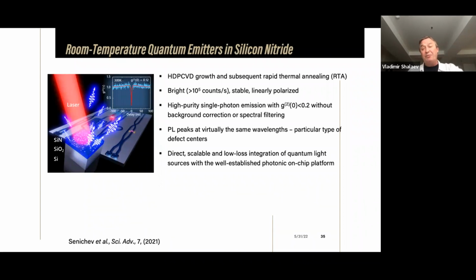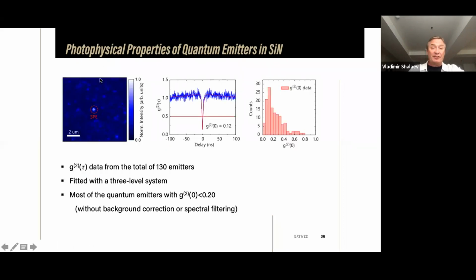Photoluminescence peaks tend to be at the same wavelength, which indicates that we are dealing with one particular type of defect center. And of course, this is a very well-established material platform, which could make a difference in terms of integrated quantum photonics. So here we just show a photoluminescence map of many single photon emitters. We picked one particular emitter and measured g2. In this case, it's 0.12. We characterized g2 for 130 emitters, and actually most of them have g2 below 0.2. And it's important that we did it without any background correction or spectral filtering.